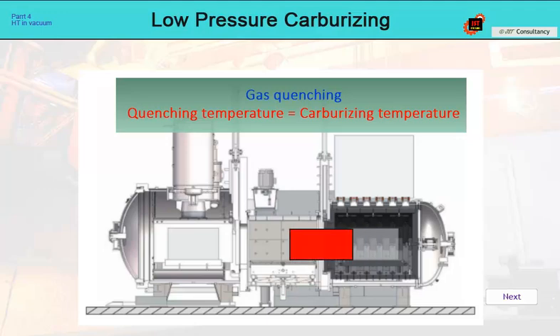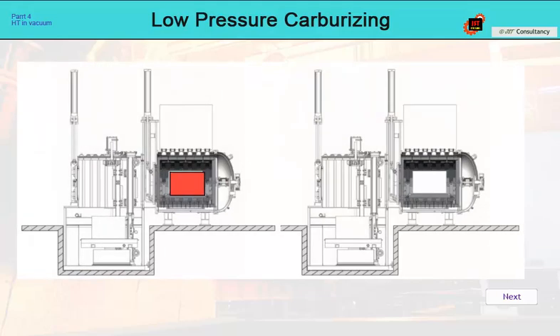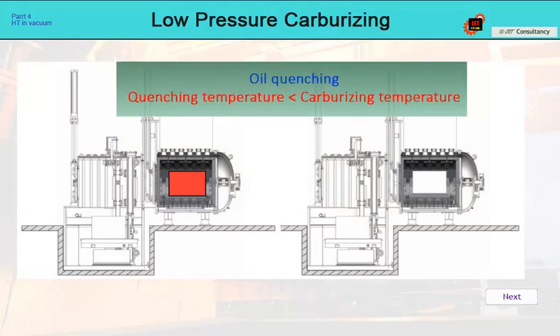If we have a 2-chamber quenching furnace, in the case of gas quenching, we quench directly from the carburizing temperature. The load is transferred from the heating cell to the quenching chamber and is cooled by the gas overpressure. In the case of oil quenching, we must pre-cool the load to the optimal quenching temperature. This can be done in 2 ways. Either we let the carburizing chamber with the load cool down to the required temperature, and as soon as the entire load reaches the required quenching temperature, we transfer it into the quenching chamber with the oil and quench it. Or we can transfer the load to the cold chamber, cool down in this chamber by spontaneous cooling or under a fan, and then introduce it back into the carburizing chamber for reheating. But this time to the optimal quenching temperature.